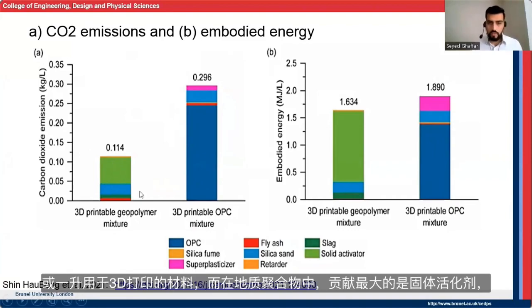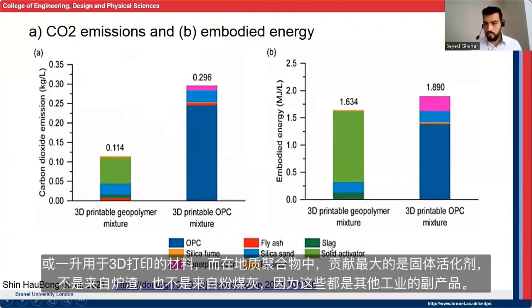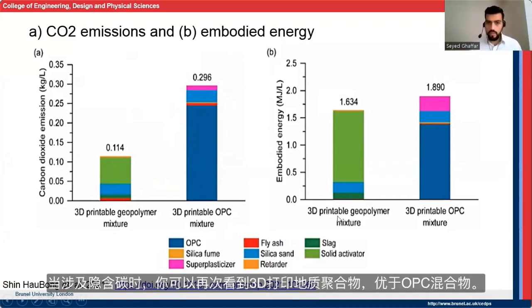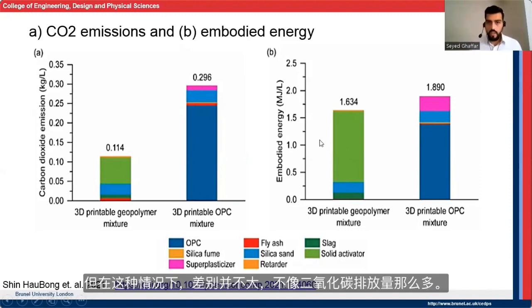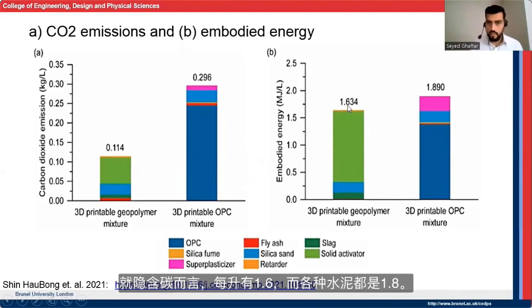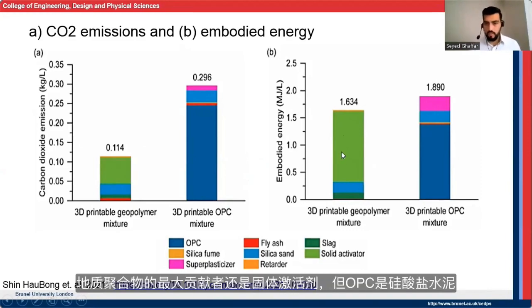Whereas in the geopolymer, the highest contribution comes from the solid activators, not from the slag or the fly ash, because these are byproducts of other industries. And when it comes to embodied energy, you can see that the 3D printable geopolymer again outperforms the OPC mixture. But in this case, the difference is not as much as for carbon dioxide emission. In terms of embodied energy, in megajoules per liter, we have 1.6, whereas ordinary Portland cement is 1.8. And the biggest contributor for geopolymer is, again, solid activators, but for the OPC system it is the Portland cement.